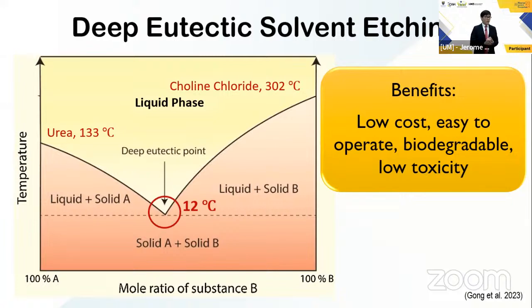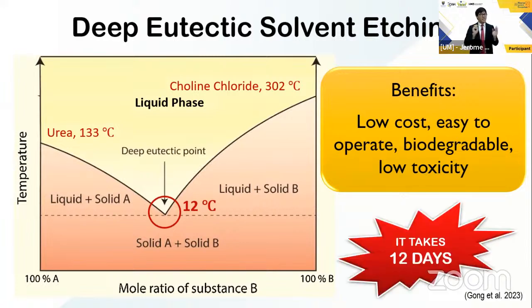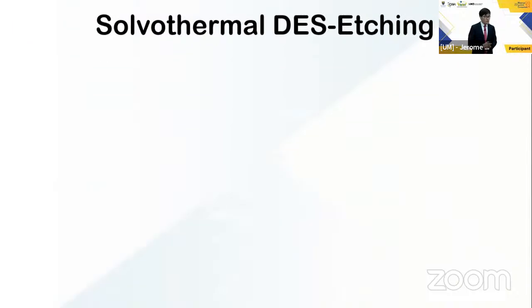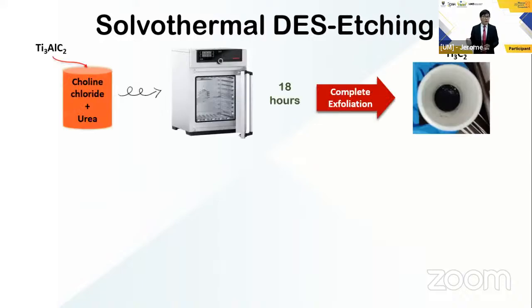Do you know what this 12 is? It was the number of days it took for a complete exfoliation. This is totally unacceptable considering you can actually make MXenes in less than 24 hours. So to address this, to promote green synthesis of MXenes, we employed a solvothermal assisted etching using DES, and we achieved a complete exfoliation in just 18 hours. This is a breakthrough for green MXenes.